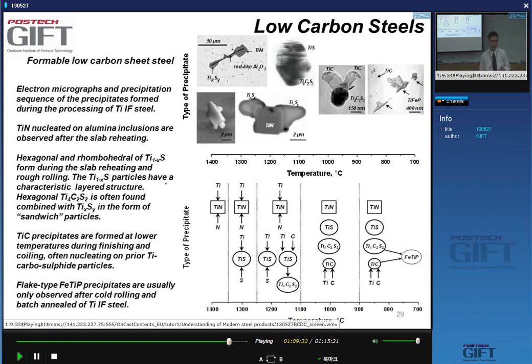But there is one big exception to this rule, and that is the carbosulfides. Carbosulfide formation is the only way you can precipitate carbides at high temperatures in austenite. But of course, you cannot form them if you don't have sulfur. And you form them at high temperatures, at the right temperature. During slab reheating, if you're at the right temperature, slightly below the 1250 we use normally, then you can form this. And so this allows you to stabilize carbon in austenite at high temperature.